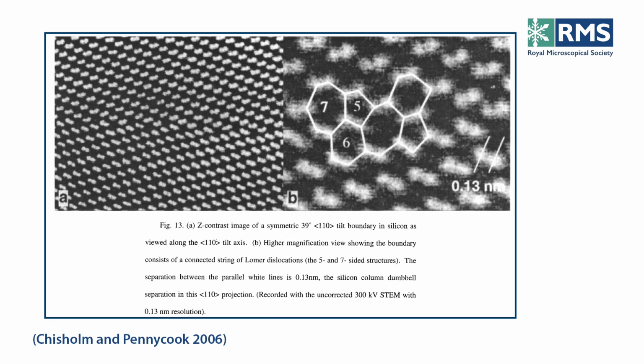The next one shows a picture of a Z contrast image, an incoherent image, of a tilt boundary in silicon. And the resolution there to resolve the grain boundary, and the resolution in the dumbbells, is about 1.3 angstroms, which is a tenth of Menter's platinum phthalocyanine. And these pictures are really very, very impressive. I should say that the STEM was developed for seeing individual atoms by Crewe many, many years ago, but then not used because of the lack of resolution, really.